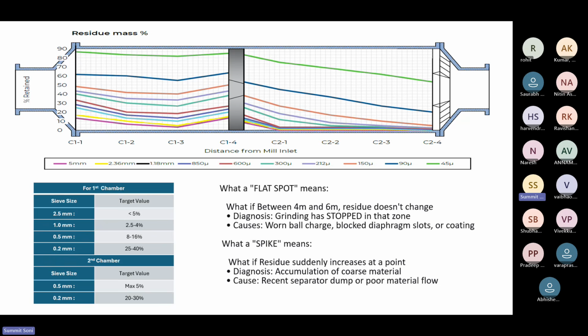What if there is a spike? What if your residue goes up? The very obvious reason will be that there's an accumulation of coarse material happening. It's not moving ahead, which means it's not flowing. Most of the time, it's either the diaphragm that is jammed, or the airflow across the mill is not proper, or there might be a separator dump or something. But as a thumb rule, we have some values which we adhere to when we are judging an action sampling.